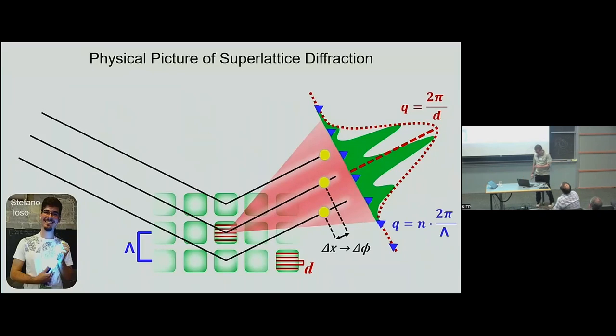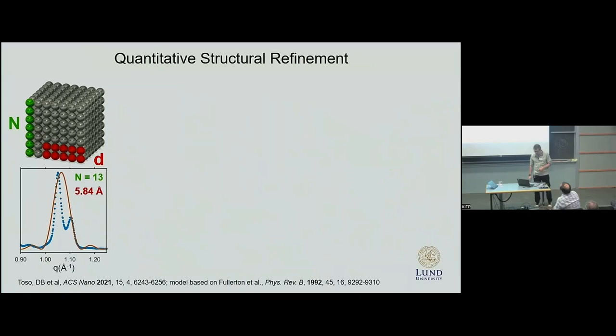By having this qualitative understanding of the phenomenon, we developed a quantitative model, which allowed us to take this X-ray data and extract as much as we can about our nanoparticles. For instance, we can set or feed the nanocrystal size, which would produce this broad Bragg peak.